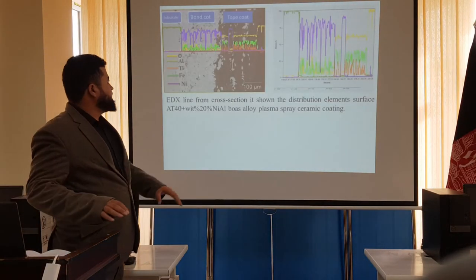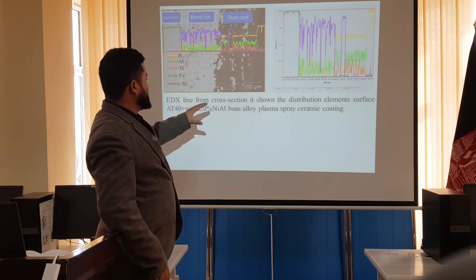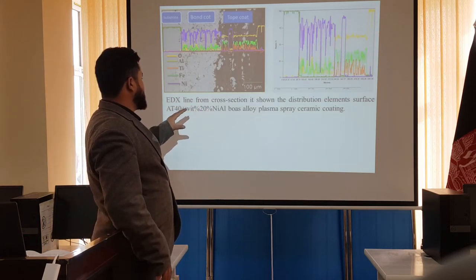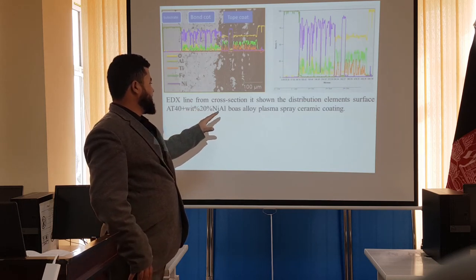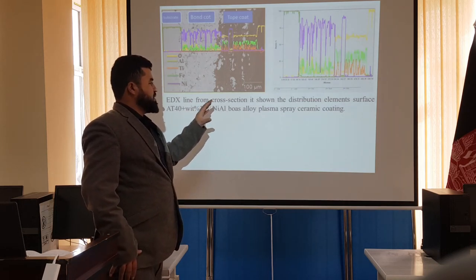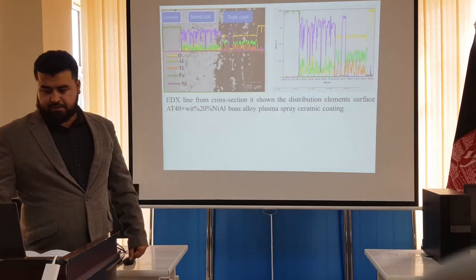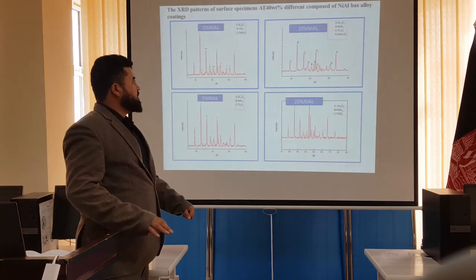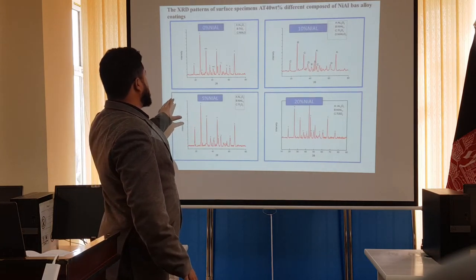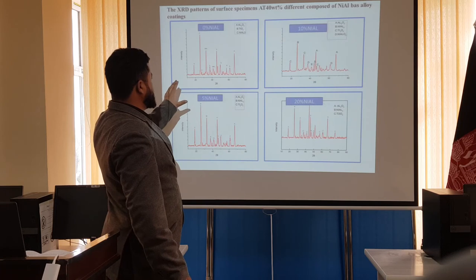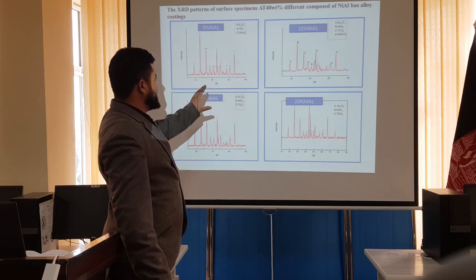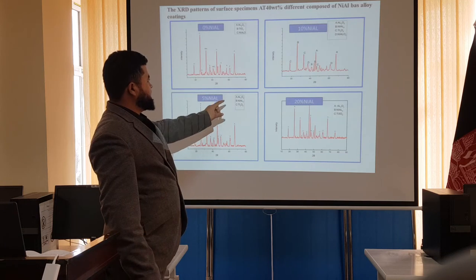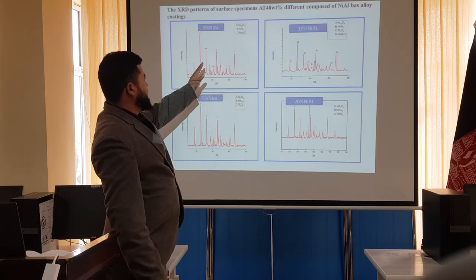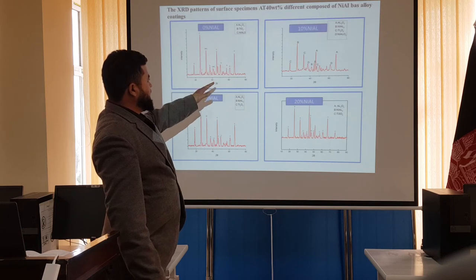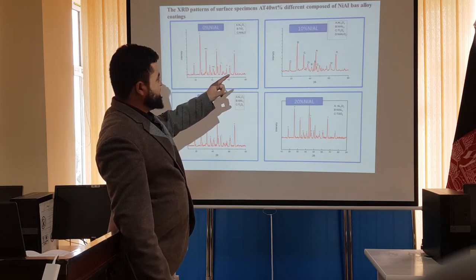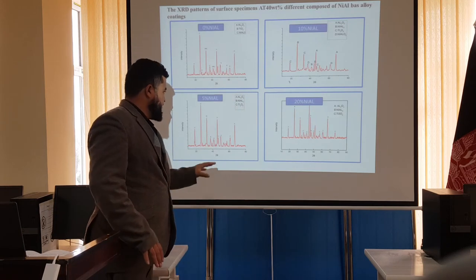We did EDX line scan for the distribution of elements on the surface of AT40 plus 20% nickel aluminum based alloy plasma spray ceramic coating. We did XRD from the surface. We checked the element composition and surface of our samples at 0%, 5%, 10%, and 20%. We have alumina, titanium, nickel, and aluminum phases like this.